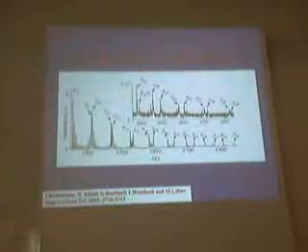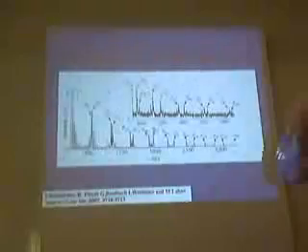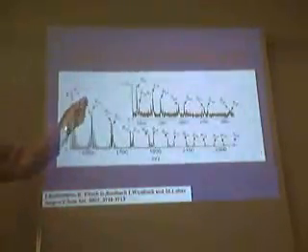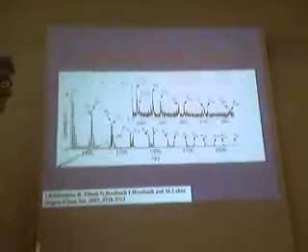With my friend in Paris, Gérard Bolbach, who is an expert in mass spectrometry, and since mass spectrometric analyses must be done very carefully, we did the experiments both in Rehovot and in Paris. Bolbach also has the MALDI-TOF/TOF way to analyze these particular samples, and he could show that this n-1 is in the two wings of the chain. Either the chain starts with one molecule which is heterochiral, or there is a termination of the growth of these chains by a heterochiral molecule. So this was done with N-carboxyanhydrides.